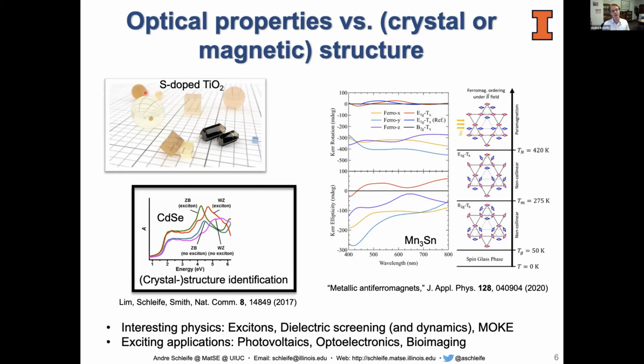So one example that we have started to look at is the connection of optical properties and crystal structure. In this case, the system here is cadmium selenide. That is a collaboration with Andrew Smith here. He's a faculty member in bioengineering on campus here at UIUC, and he makes nanocrystals of this material in his lab. So he synthesizes them, and his question was whether it's possible to distinguish that material in its zinc blende structure from its wurtzite structure purely based on spectroscopy. The reason is that these nanocrystalline samples are not so compatible with high or ultra high vacuum techniques or X-ray diffraction, and so if he has a spectroscopic approach to distinguishing these two crystal structures, that would tremendously benefit his research.